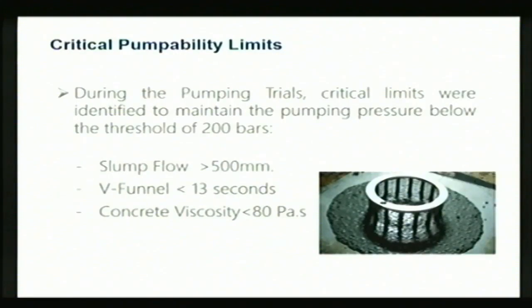And as I said, 13 seconds was the limit, but we found out that we actually needed much lower than 10. I mean, we could still pump with the below-13-second V funnel. But to really have a proper flow that keeps the concrete going, you needed 8 to 10 seconds.